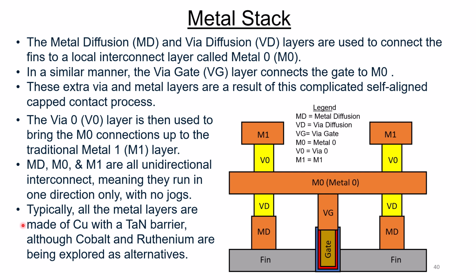So let's take a look at the metal stack. The metal diffusion MD layer and the via diffusion VD layer are used to connect the fins to a local interconnect layer called metal 0. You can see the fins are down here in the bottom, and we have the MD and VD layers here connecting the fins up to a metal 0 layer. These extra via and metal layers are the result of this complicated self-aligned capped contact process. Now, in a similar manner, there's a via gate, VG layer, that also connects the gates up to a metal zero layer. So the via zero layer is used to bring the metal zero layer up to the traditional metal 1 layers.